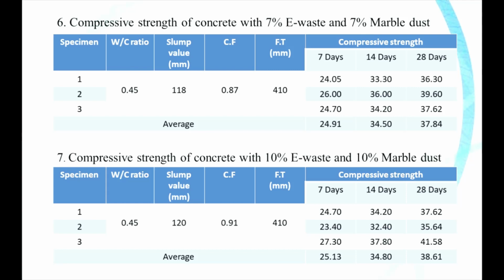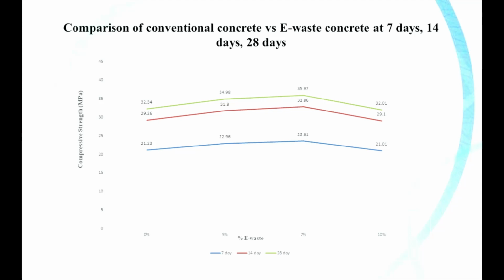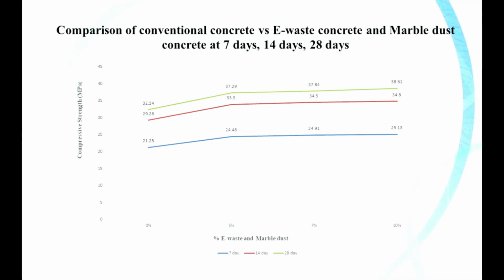So moving towards the next slide, this is the graph showing the comparison of conventional concrete versus e-waste concrete at 7 days, 14 days and 28 days. As we see in the graph, there is a peak strength gain at 7%. The strengths are 35.97 megapascal and 32.86 megapascal and 23.61 megapascal. So at 7% there is an increase of strength, and after that there is a slight decrease of strength at 10%.